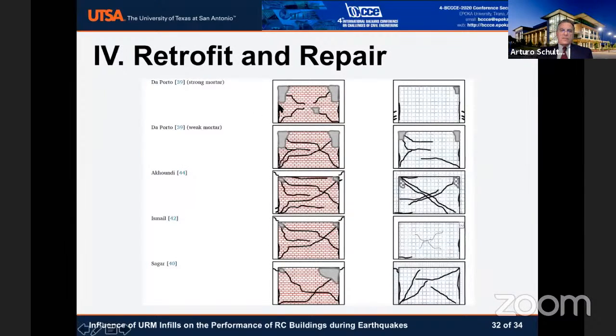Here you see some drawings of buildings that were tested, frames that were tested in the laboratory by a number of researchers, where you have brick infill and a reinforced concrete frame. You see the crack and the crushing damage that occurred during the test. And then the sister frames that were built the same way, but had textile reinforced masonry overlays. And you can see that with the exception of this case in the middle, all of the others developed a fair amount less damage as they were loaded to the same number of cycles and peak displacements than their counterparts.